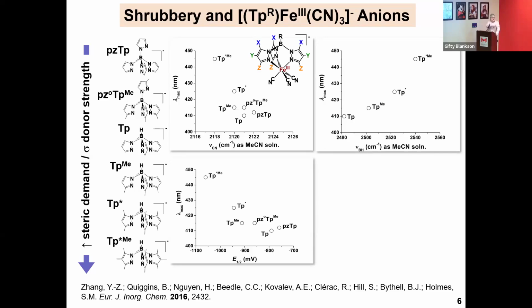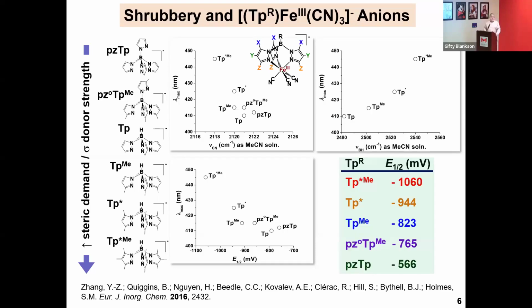If you look at the electrochemical potentials, things that have lots of donor groups on the pyrazolylborate tend to give very large and negative E1/2 potentials, meaning E1/2 is defined as the energetic cost, voltage-wise, of reducing the iron 3 to iron 2 reversibly. So that is the so-called iron 2,3 redox couple. For very electron deficient ligands, such as these, you can see it's a much more positive potential, meaning it's much easier to reduce that iron 3 to iron 2. And that's going to become important.